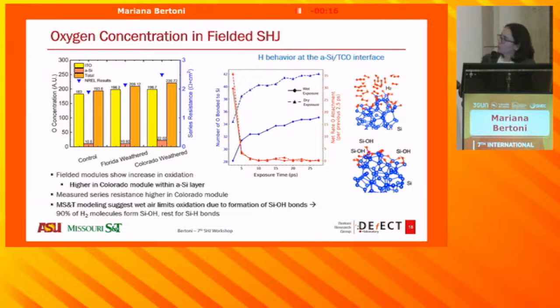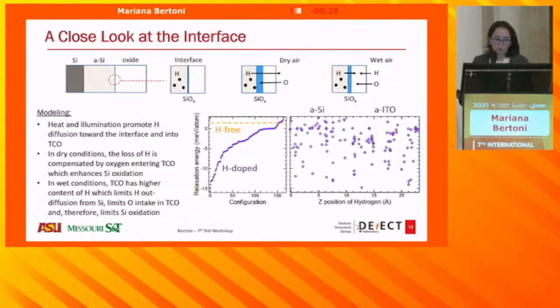But the truth is that when you start looking at some molecular dynamics, you see that the number of oxygen bonded to silicon in the dry exposure is much higher than what you get in the wet. I'm almost done. So the moral of the story is that heat and illumination promote the hydrogen diffusion towards the interface and into the TCO. In dry conditions, the loss of hydrogen is compensated by the oxygen actually entering the TCO, which enhances the silicon oxidation.